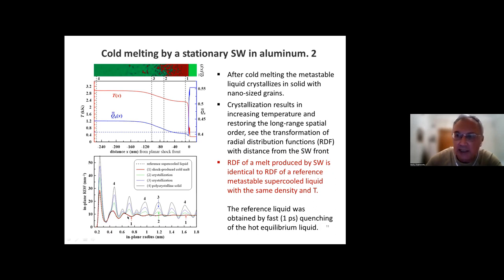I have to say here an important thing about the radial distribution function. The radial distribution function here in the supercooled metastable melt produced by the shock wave is identical to the RDF obtained in a reference metastable liquid with the same density and temperature. And this reference liquid was obtained not under shock loading, but by very fast quenching of the hot equilibrium liquid.